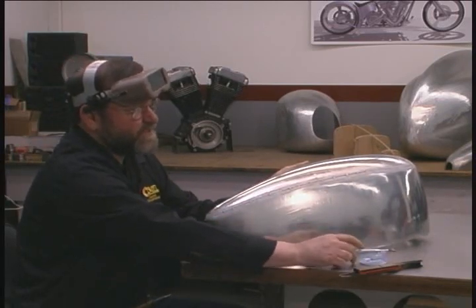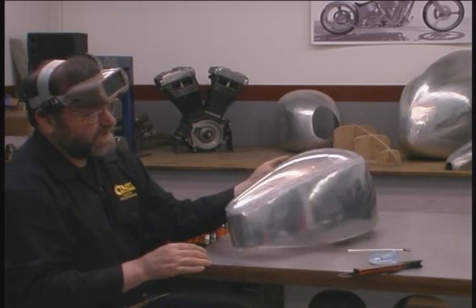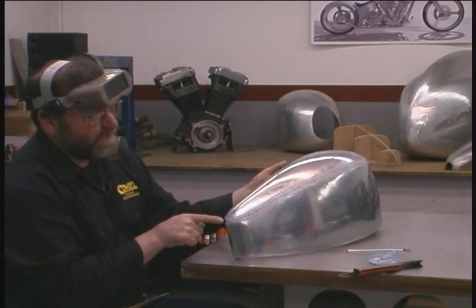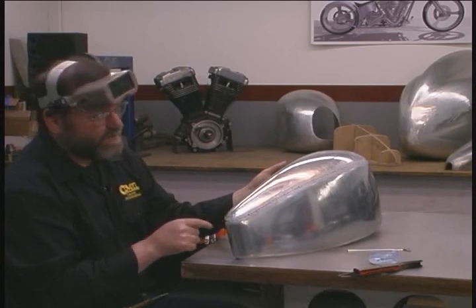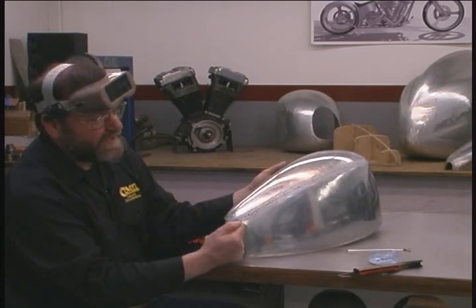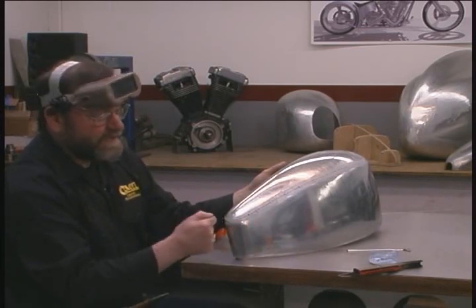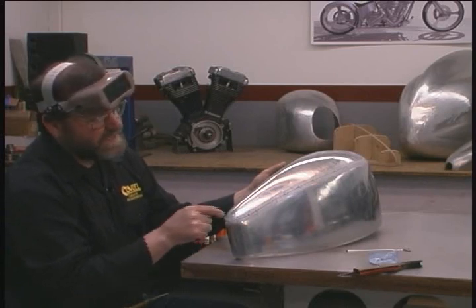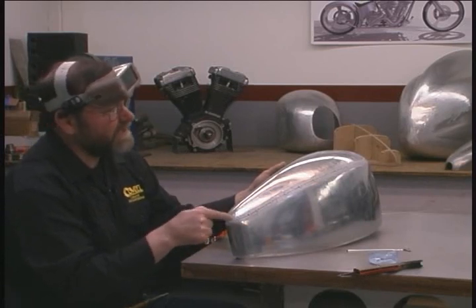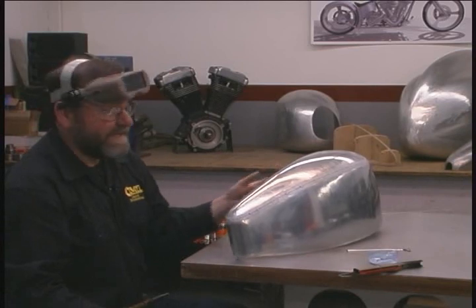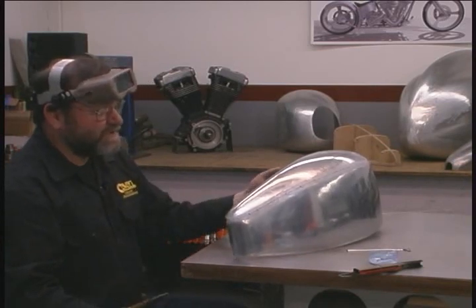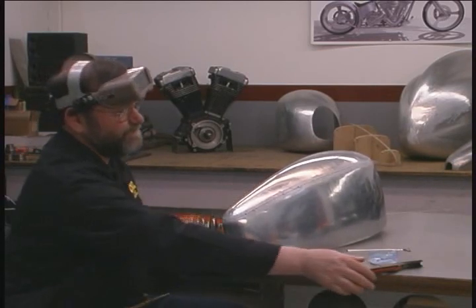Now, when you're gas welding aluminum, it's very important that you do not start the weld right at the end of the joint. The proper procedure is to start the weld about 1 inch away from the end and then weld to the end. Once that's done, you can start at the beginning of the first weld and weld all the way to the other side. You'll find that this will go a long way toward preventing cracking of the weld.